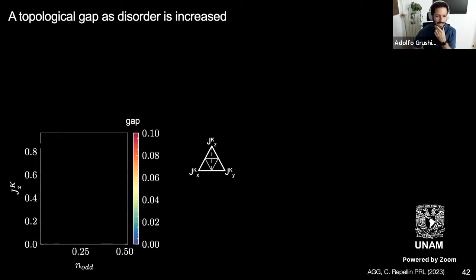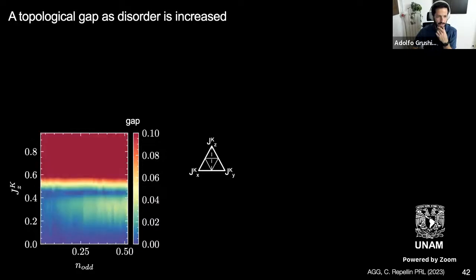So now I'm going to show you a phase diagram, which goes from top to bottom in this Kitaev phase diagram, and on the x-axis is the density of odd plaquettes. Remember that this phase here in the upper triangle is trivial and gapped. This is gapless, and this will be here on the left edge. What you see here is the gap, and for a region of the parameters the gap is pretty large, and then it becomes gapless. But if you tune the density of odd plaquettes a little bit, you'll see that you have another gap, which is a little bit smaller, a trivial gap, but still sizable.